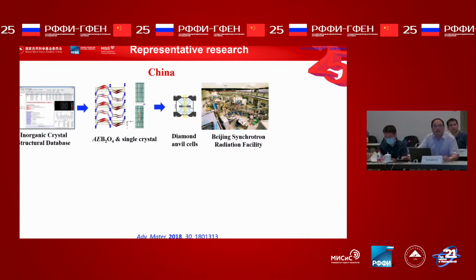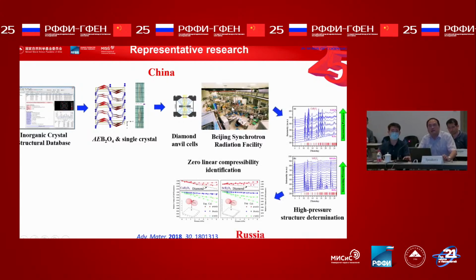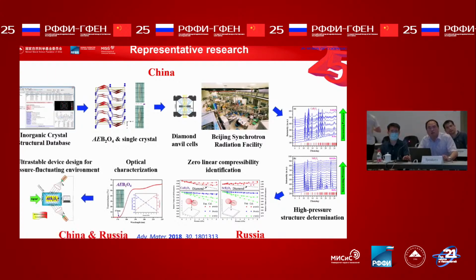So we grew the single crystals and measured their mechanical properties in the high pressure station at the Beijing synchrotron radiation facility. As the high pressure XRD data are very complicated, the Russian team analyzed the structure evolution and confirmed that this compound exhibited the zero linear compressibility. Moreover, these crystals exhibit very good transparency down to the deep UV spectral region. By combining these two interesting properties, we designed an ultra-stable device for the pressure fluctuating environment.